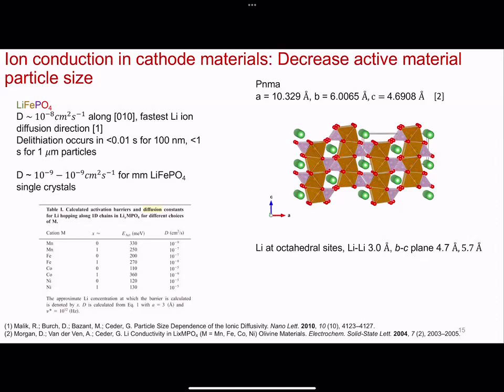And so the paper I cited here, the Morgan and Ceder paper from 2004, and the Malik and Ceder paper from 2010 as well. The 2004 is actually the table here. They worked it out from first principles, and they mapped out exactly as you decrease the particle size what the percentages of defects are that you're going to get, and that's how you increase ion diffusion as you decrease the particle size, which means now your material can diffuse faster and thus operate at higher C rates. And so when people say lithium iron phosphate is one of the few materials that can work when nanostructured, that is why.